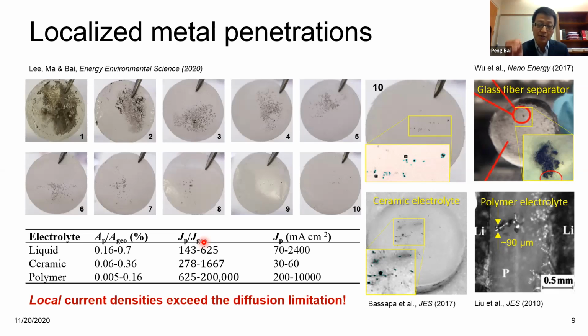But when penetration starts to occur, when you go inside a separator to just a few pores, the local current is then very, very strong. Okay, so that easily goes beyond diffusion limitation and it can trigger dendrite growth. And then you can see this explains why we have the controversy introduced earlier, that penetration happens locally.